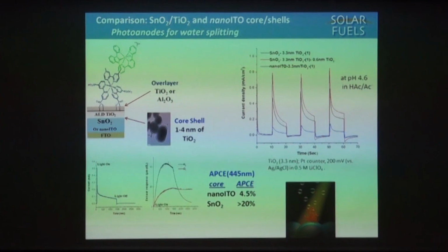The reason we do that is that it turns out if you look at the potentials of the two materials, when you inject in the TiO₂, the electron that goes down in the tin oxide, there's a 0.4 of a volt difference between the two. That means the back electron transfer, once injected through the TiO₂, has to go uphill 0.4 of a volt. All of a sudden, the efficiency jumps up to 20%. And here you can see sustained photocurrent, and here direct measurement of the products, hydrogen measurement, oxygen present, using microelectrodes.